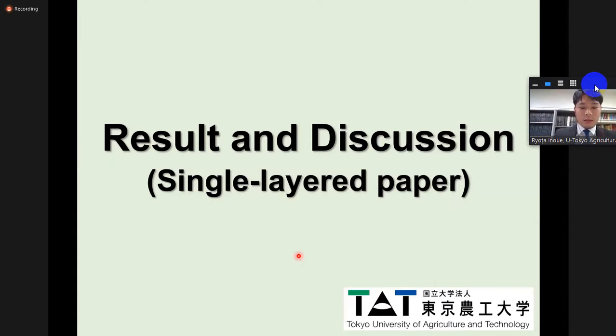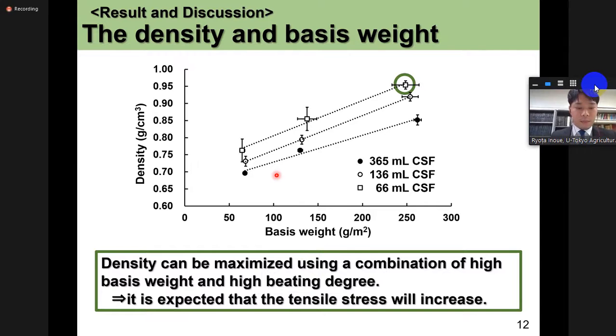I'd like to move on to the results and discussion. This figure shows the relationship between the density and the base weight of the single-layered paper prepared with different freeness values. There is a positive correlation between the density and the base weight. As you know, with the same base weight, the density increases as the beating degree increases. The important point here is that density can be maximized using a combination of high base weight and high beating degree. Therefore, it is expected that the tensile stress, wherein the tensile breaking load is corrected by the cross-sectional area, will increase.